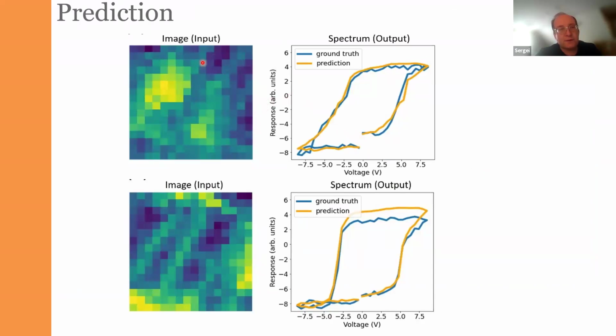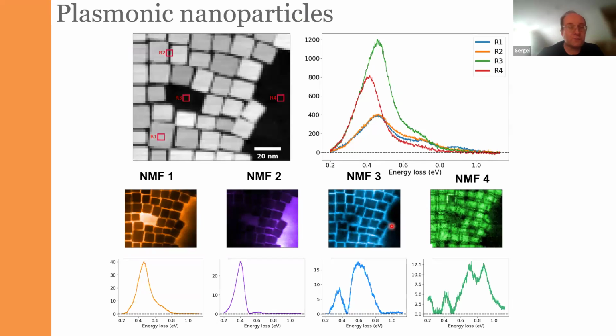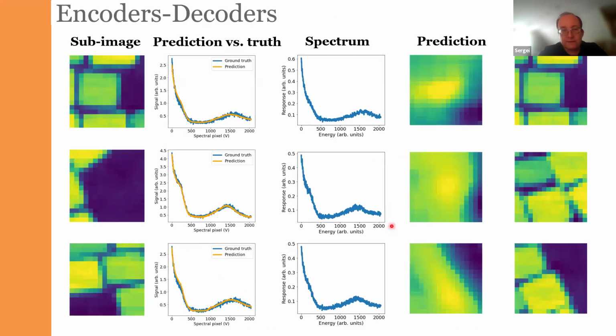So for example, this is the prediction where our input is the domain structures and the outputs are the spectra. So obviously this is a test example. This is not the training data set. And you can see that the prediction and the ground truth actually match reasonably closely. And this is another example where, I mean, it's not perfect, but good enough. So this works for scanning probe microscopy. This works for EELS data sets. So in fact, we can make it work in both directions. We can take the image and predict the EELS spectrum from it. And then we can take the spectrum and try to find out what the image would be.